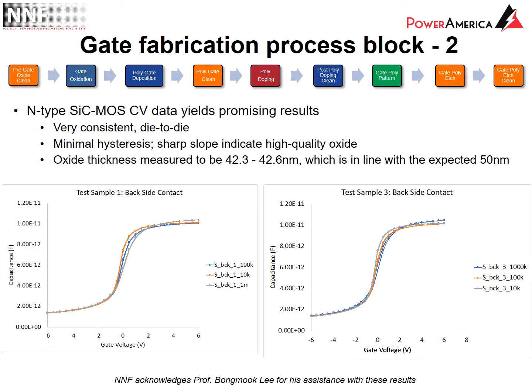The next step, of course, was to oxidize silicon carbide and make a similar device, instead of a silicon metal oxide semiconductor device, a silicon carbide metal oxide semiconductor device. And we were able to go ahead and do that at high temperature, oxidize the silicon carbide and make the device. And we were particularly pleased with these results.